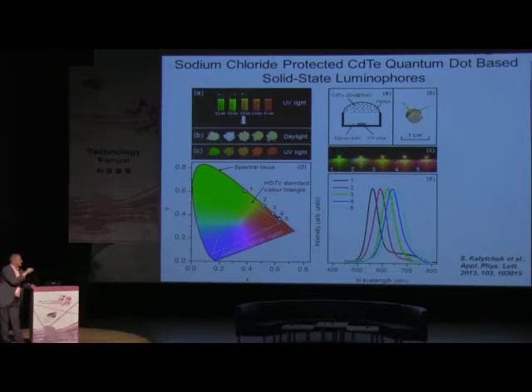And if we mix them together, we very efficiently protect cadmium telluride from the environment by embedding them into such a powder, like you can see here, where they are surrounded by salt. So we call them salty dots. And you can see that these powders emit any color of light which is possible to achieve with cadmium telluride quantum dots, from green to red.